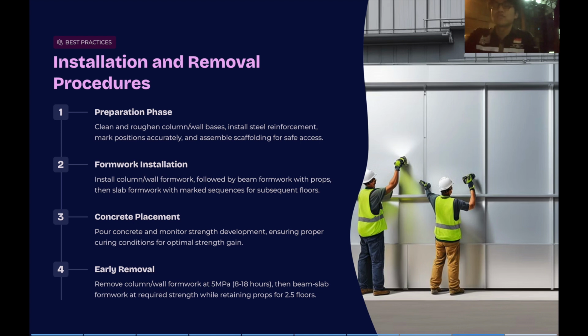And then the installation and removal procedures. For the first one, preparation phase: clean and roughen column or wall bases, install steel reinforcement, mark positions accurately, and assemble scaffolding for safe access. Then the next one is formwork installation: install column or wall formwork, followed by beam formwork with props, then slab formwork with marked sequences for subsequent floors. Then the third one is concrete placement. Place the concrete and monitor strength development, ensuring proper curing conditions for optimal strength gain. And for the early removal, remove column or wall formwork at 5 megapascal, around 8 to 18 hours. Then beam slab formwork at required strength, while retaining props for 2.5 floors.